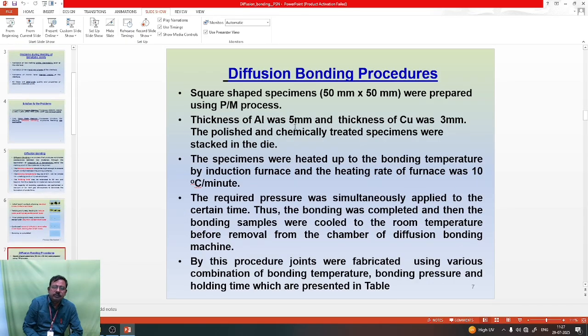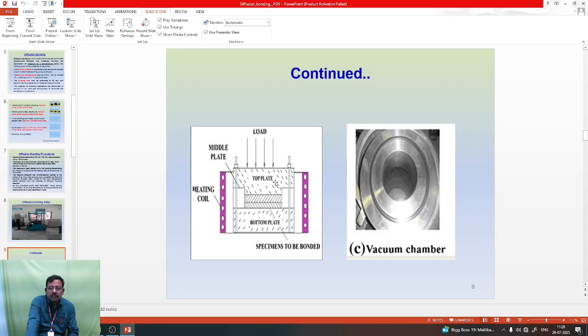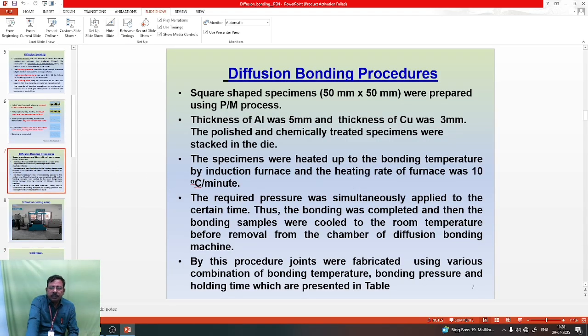The diffusion bonding procedure: here we are using aluminum copper specimens which were prepared by the powder metallurgy technique. The thickness of aluminum was 5 mm and copper was 3 mm. These metals are polished and chemically treated. Specimens were stacked. The specimens were heated up to the bonding temperature by induction furnace, and the heating rate of the furnace was 10 degrees Celsius per minute. The required pressure was simultaneously applied for a certain time. Thus the bonding was completed, and then the bonding chamber is cooled to room temperature before removal from the diffusion bonding machine. Okay, by this procedure, the joints are made.